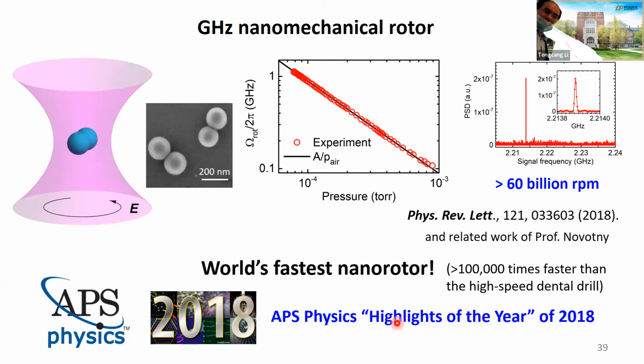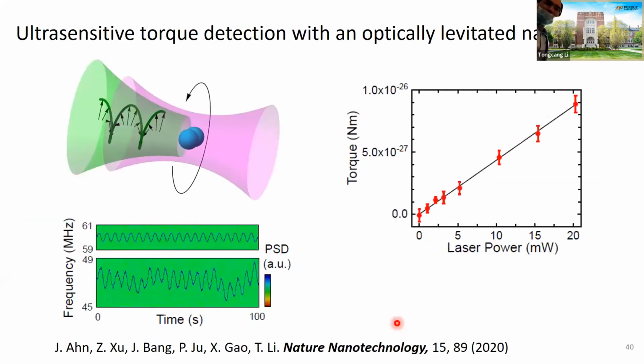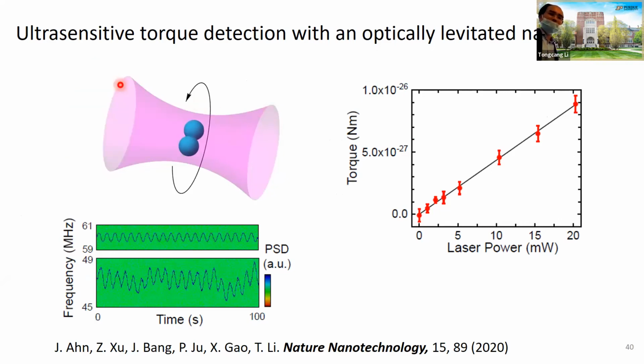Remember, our initial motivation was to detect small torque. Rotating very fast is very cool, but we want to see whether we can really detect a small torque. To do that, we add another laser. The pink or infrared laser is for trapping and detection, and then we intentionally add another laser to give a small torque, so we can see whether we can measure it.